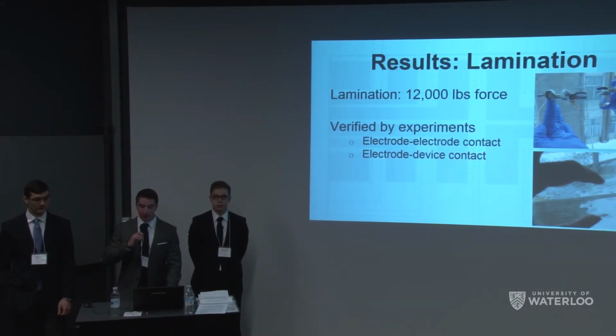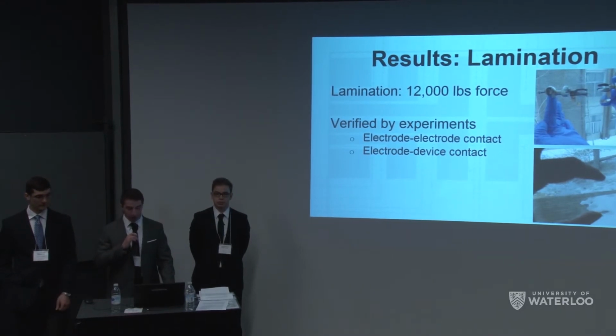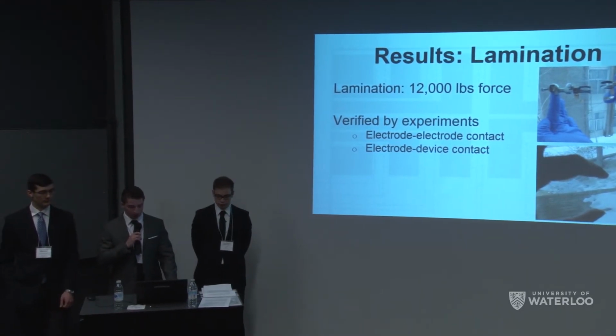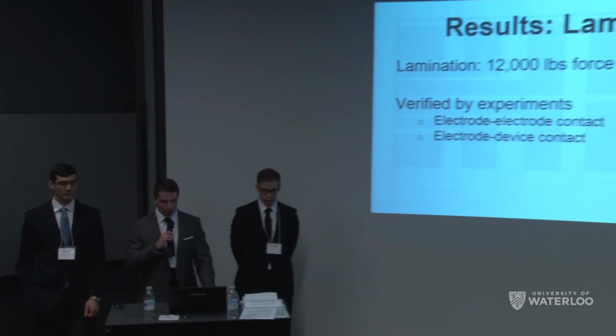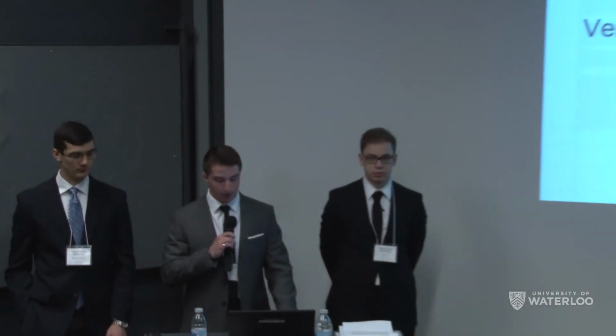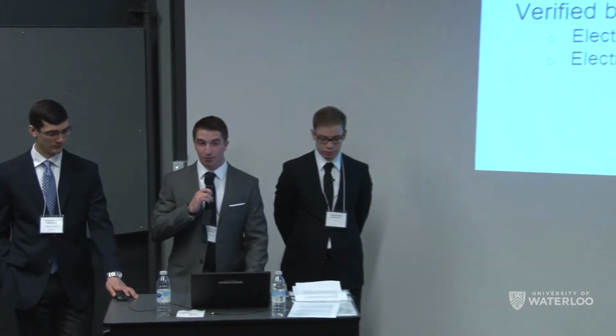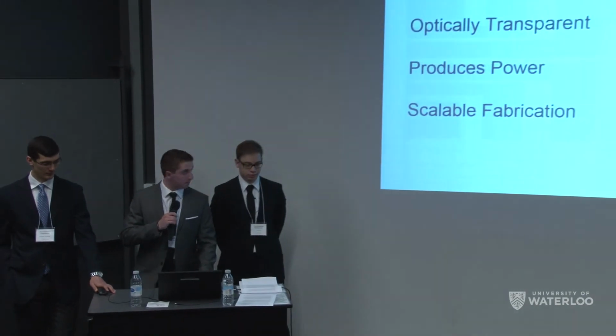More importantly, we tested the silver nanowire substrate onto a standard Schottky solar cell using the same pressure and parameters. This device provided a relatively high voltage with a low current. The silver nanowires did indeed provide the desired electrical contact to the top electrode of the device. Because of the strong electrical contact, this device's process parameters could be modified to make the top electrode thinner and thinner until it is eventually no longer required.